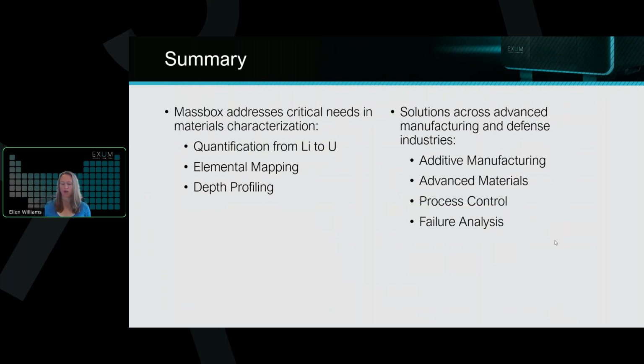And we also walked through how you could use this for process control to verify that what you're creating matches what you intended to create, what you designed. And then an example of how we would go through a defect analysis or potentially a failure analysis, where we can scan a large area, then identify an area of interest, use a smaller laser spot size, and get a really high resolution view of the defect or failure of interest. And then we can even do a depth profile to see how that failure penetrates subsurface.